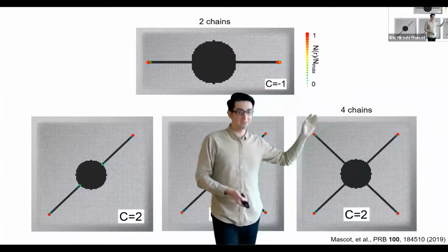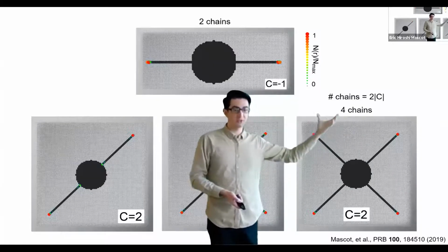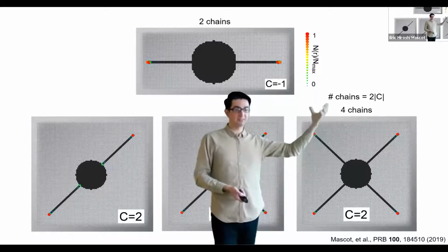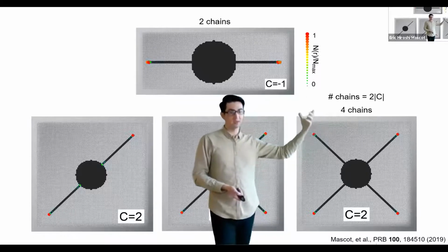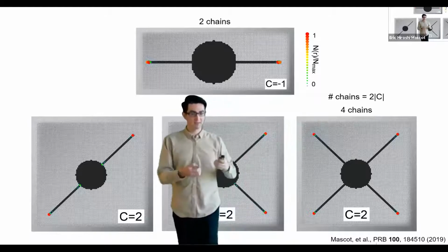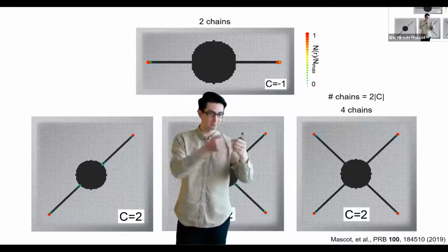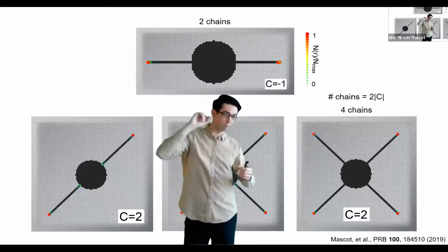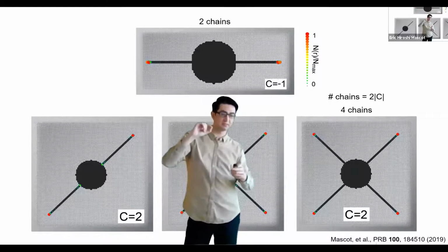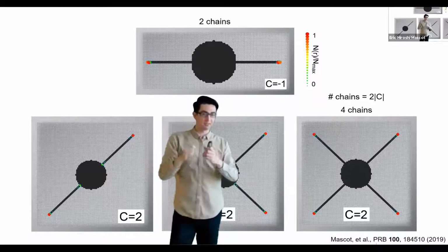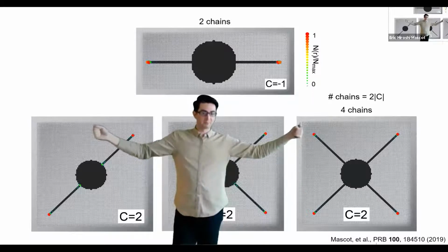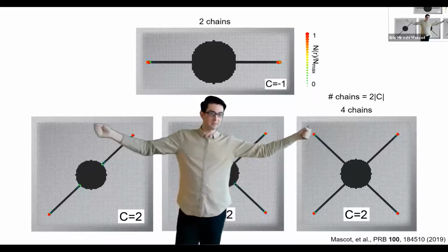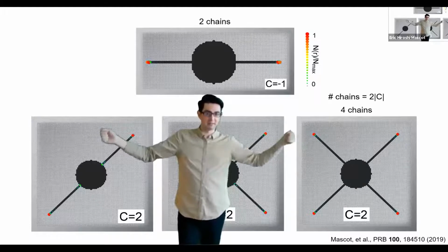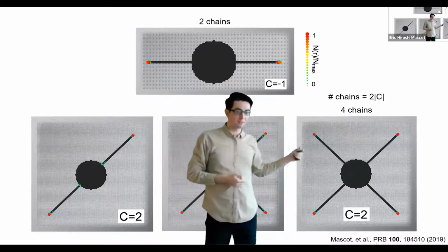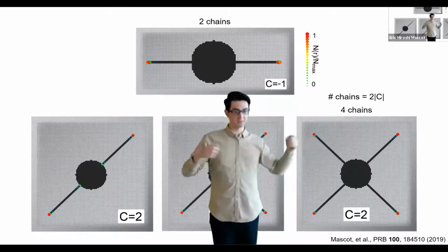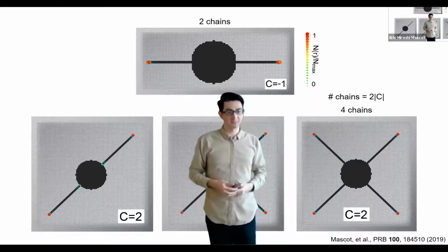And we can actually use this to count the Chern number. So the number of chains is twice the Chern number, and that comes again from the bulk boundary correspondence, where in the C equals -1 phase, you have one zero energy Majorana edge mode. And so by pulling two Majorana bound states, you pull that state out of the island. But for C equals 2, you need to do 2 of those. And so you need 4 chains.